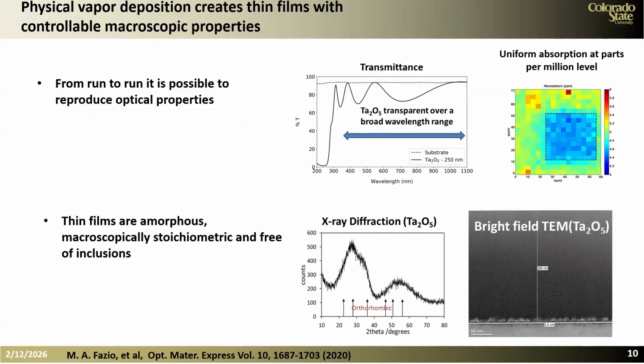Now, when you look at these materials using typically any technique, like for example, transmittance measurements, the materials are, number one, transparent over a very broad range. And this is the reason why they are so prevalent in designing coatings for lasers that operate from about 200 nanometers all the way to 2.3 micrometers. Then water absorption starts to be a problem. They are very uniform. They can be deposited very uniformly, and I show here that the absorption loss is very low over the film, over the substrate area.